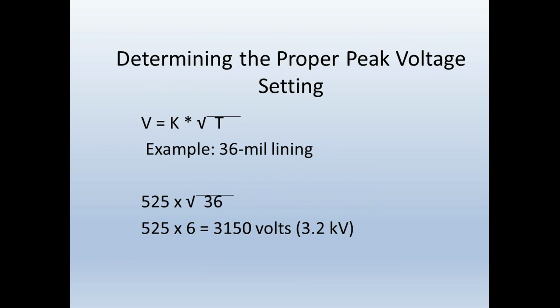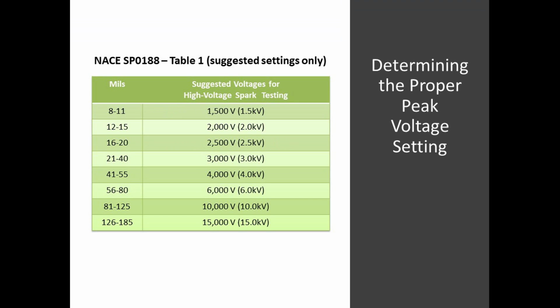The example I have on the next slide is a 36 mil lining system, just because the math is easy. Square root of 36 is 6. I'm going to multiply that by 525, because I'm less than 40 mils. I only have a 36 mil lining. That tells me that my test voltage for high voltage should be about 3,150 volts, or 3.2 kilovolt. Okay? I can set my detector to make sure I'm not going to exceed the dielectric strength of the lining, but still get a good detection if I do a pinhole.